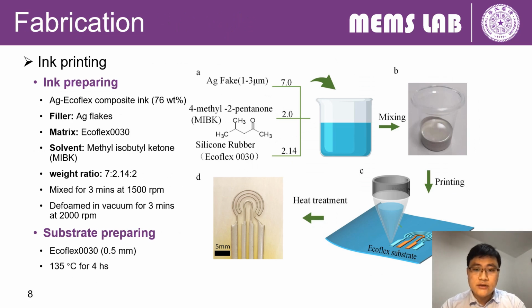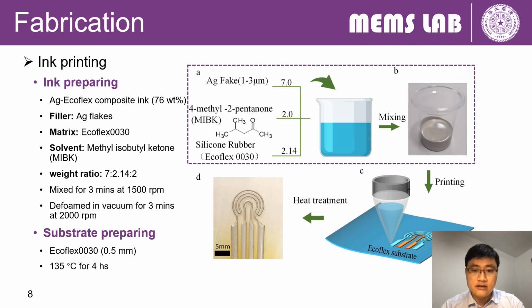Here, the figure shows the fabrication process of the sensor, which mainly includes three steps. The first step is ink preparing. Silver flakes and Ecoflex are adopted as a filler and matrix respectively to make stretchable composite ink with good thermosetting and thermosensitive properties. The concentration of silver flakes dominates the electroconductivity and stretchability of the silver Ecoflex ribbons, which is 76% here.